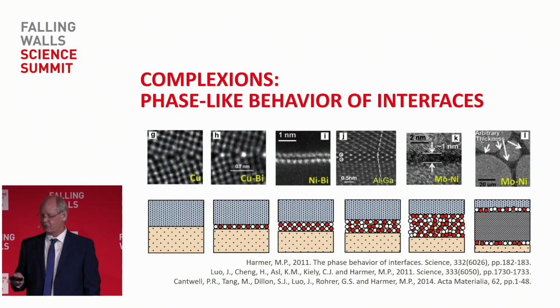The discoveries that we've made in looking at the individual atoms, shown in this figure here, have shown us that the spaces between the grains in polycrystal materials form very unique, distinct layer-like structures. The term that we use for that is complexions. These form different layer structures, and depending on the nature of the layer and the bonding in the layer and the number of layers, it can completely determine the properties of the material.